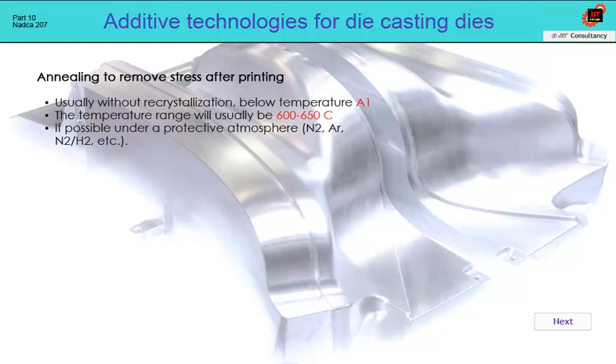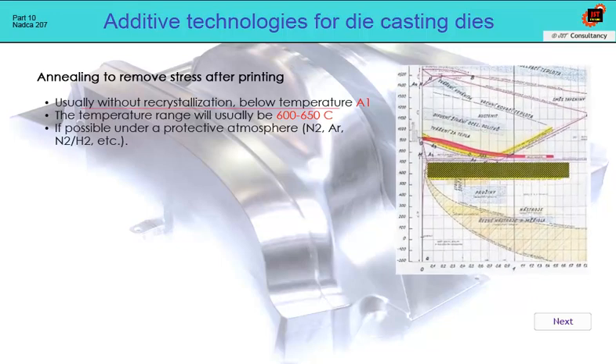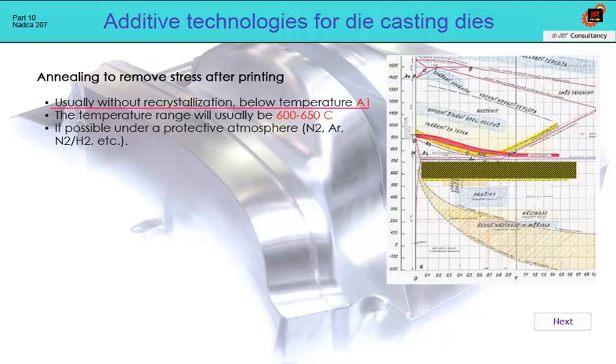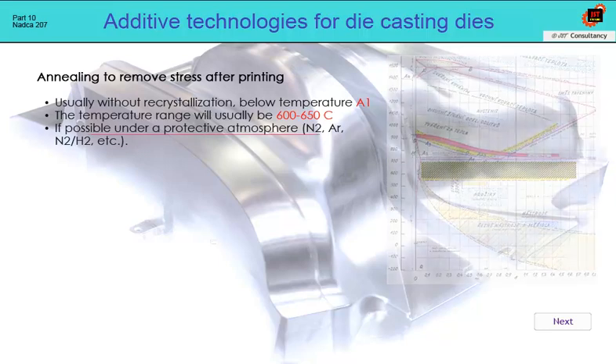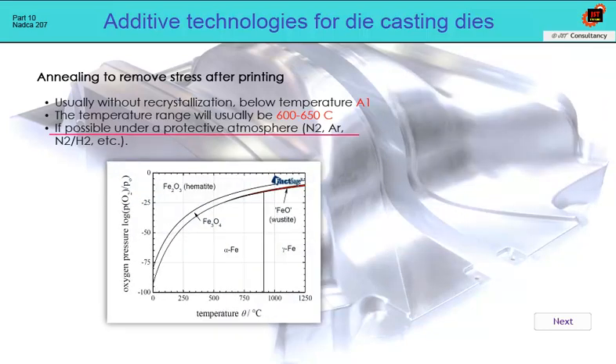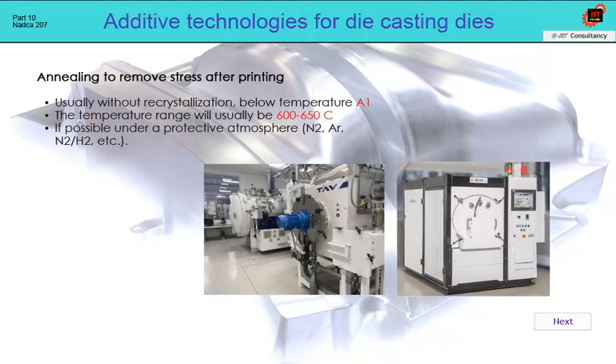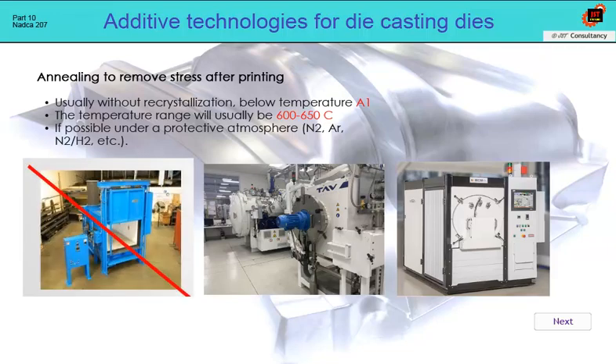Stress relief annealing is the process without recrystallization, below temperature A1. The range from 600 to 650 Celsius is usually used, but it depends on the material from which the product is printed. Since annealing takes place at temperatures where oxygen diffusion can already play a significant role, it is necessary to anneal in a protective atmosphere or, even better, in a vacuum furnace. This is the only way to prevent oxidation along the grain boundaries, which can worsen the impact strength of the material. Stress annealing without a protective atmosphere is not recommended.